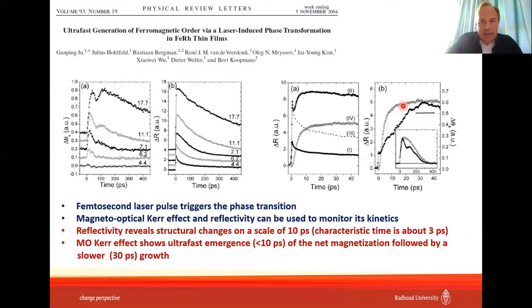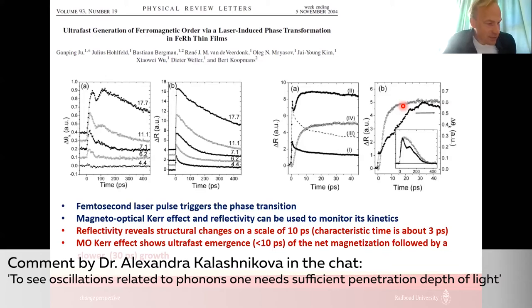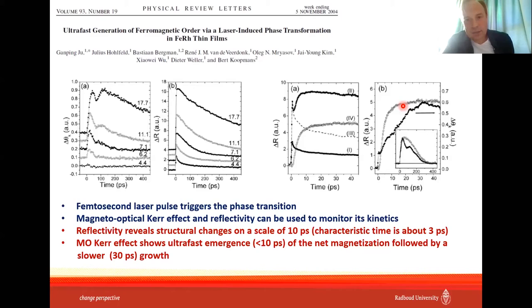Well, I'm not sure that this mode should be on a time scale of 10 picoseconds. Still, I think that the internal mode of a thin film can be. But then another question is whether the oscillations will be damped here. So also Alexander says that for oscillations related to phonons, one needs sufficient penetration depth of light. Also true. And I believe it should also be quite a homogeneous situation, because otherwise any inhomogeneities will contribute similarly to inhomogeneous broadening. Again, it would look like a heavily damped oscillation, even if it is there.